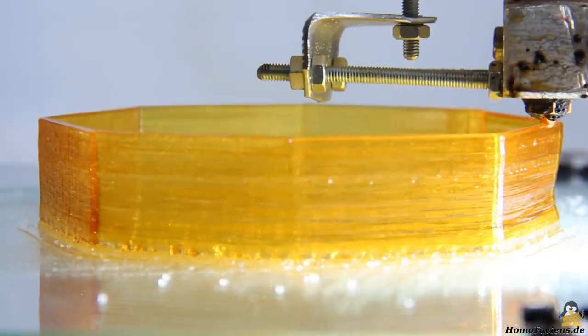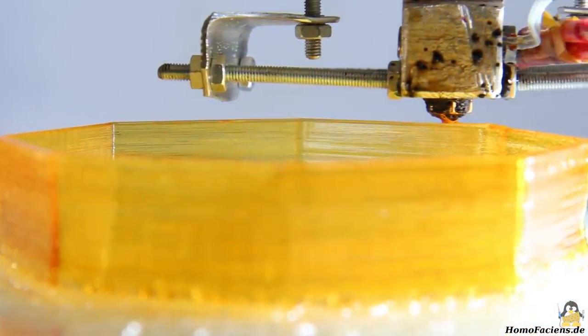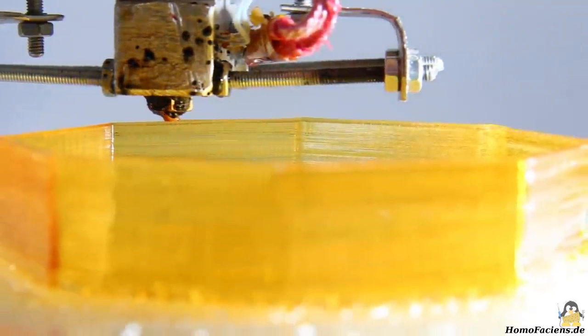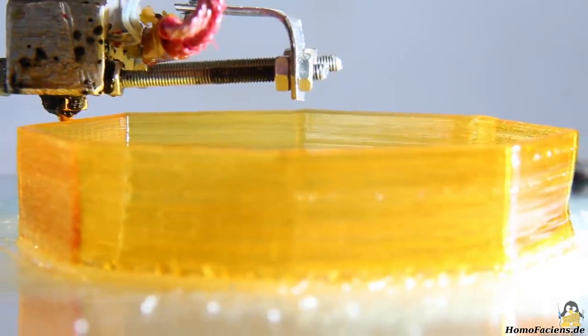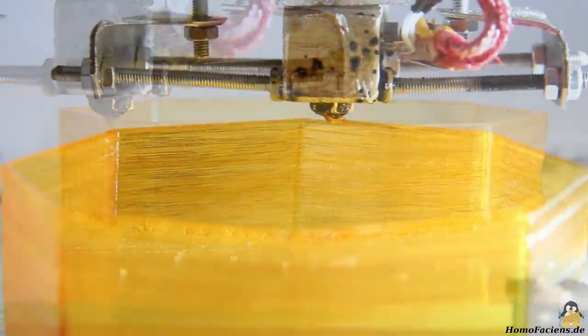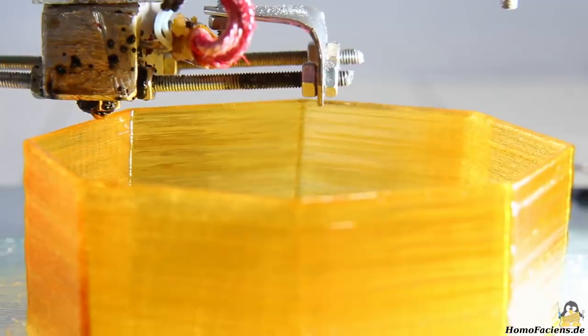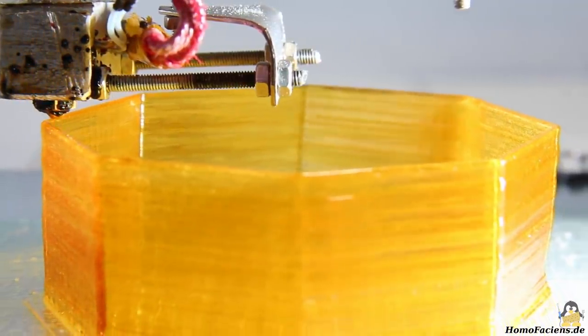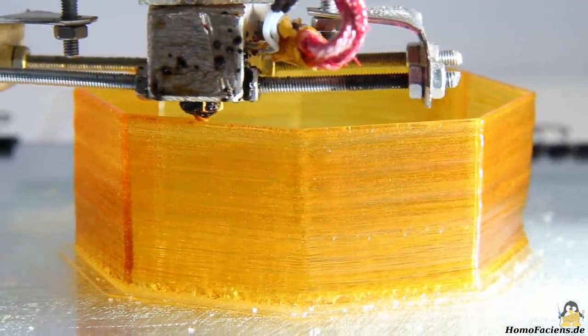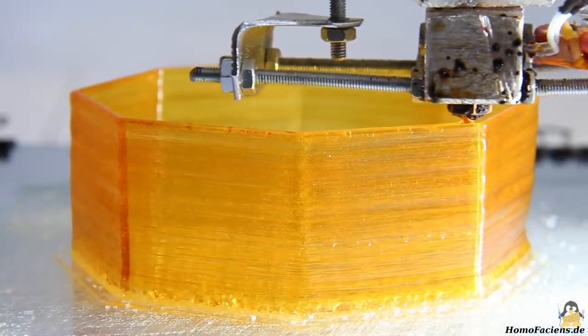There are 50 shades of brown in the different layers. The handmade extruder has so-called dead spots — corners where the sugar stays in place a little longer until it is flushed out of the nozzle, and longer caramelization leads to a darker color. All in all I am satisfied with the result: the walls are quite smooth, no cracks can be seen within the layers, and the transparent sugar walls also allow a view of the inner structure.